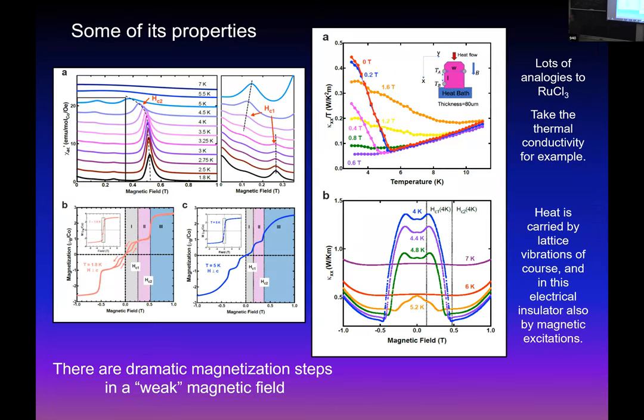Then I went to a physicist who works around me, and he measured the thermal conductivity of the stuff. He saw a rather dramatic drop in thermal conductivity as you put a magnetic field on it. Well, what does thermal conductivity come from in a solid? It comes from the electrons moving around, from lattice vibrations, and from magnetic excitations. So this says that the magnetic excitation dramatically changed at half a tesla. By 0.5 tesla, which is a nice accessible magnetic field, something happened. And when you do magnetization versus applied field, you can see that the behavior is really peculiar. There are these steps in the magnetization as you put fields of different values on it. So this is like the magic stuff.